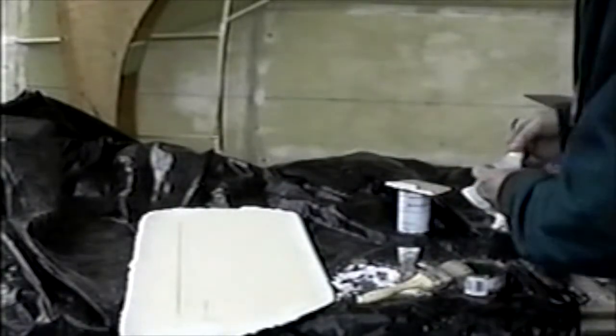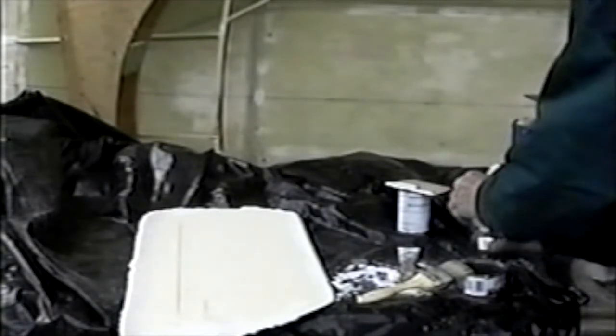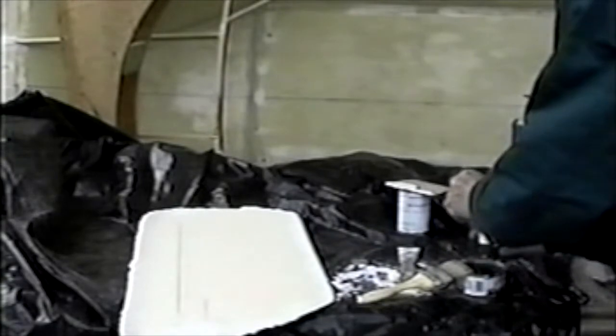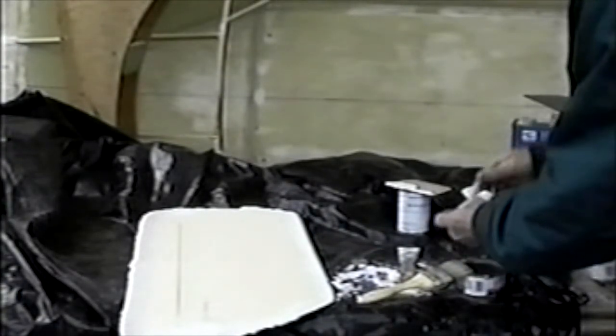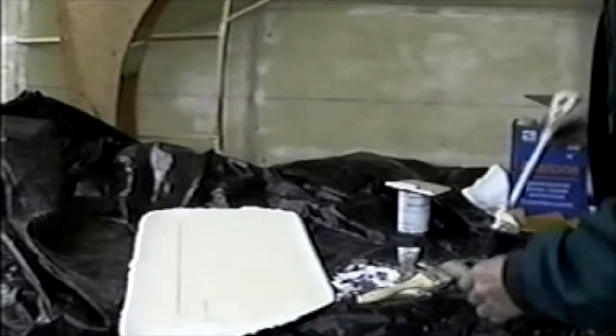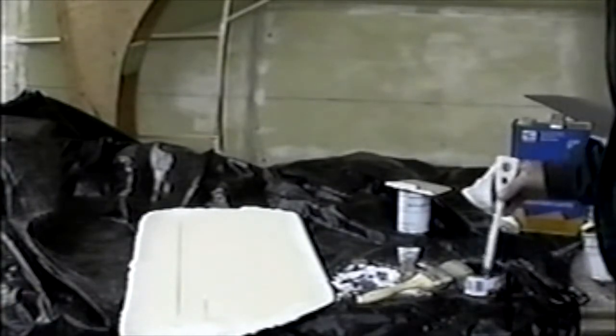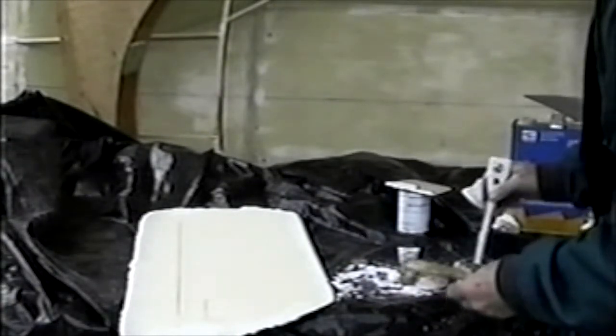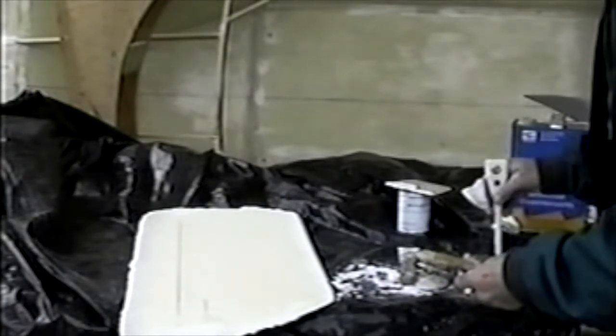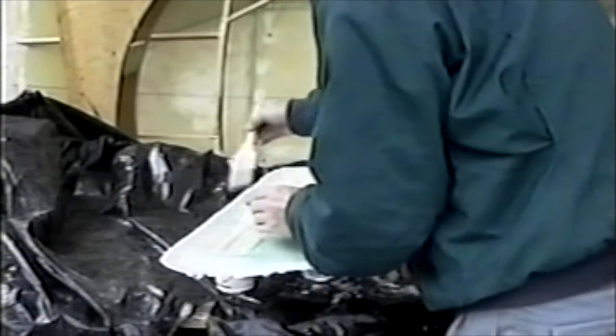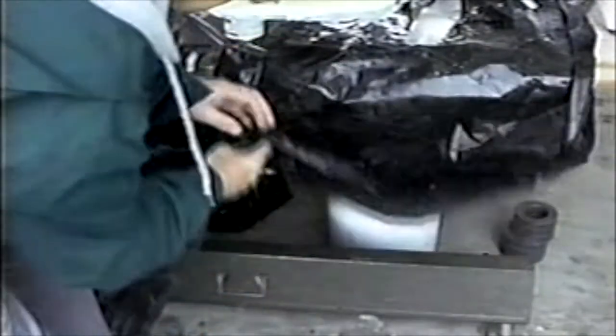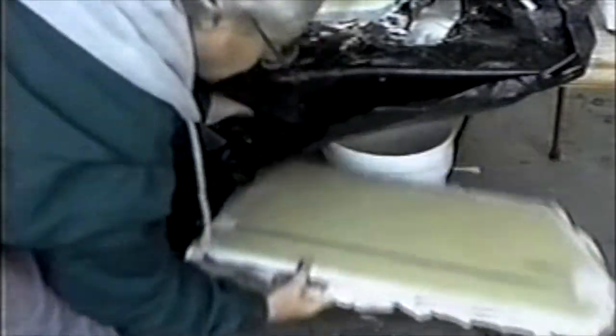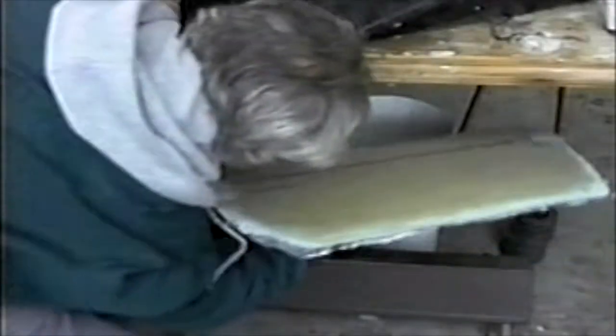Since it's 42 degrees Fahrenheit out here, we're going to catalyze the resin at 2%. We'll also use our heater device that's underneath the table to cure this layup out. It's best to paint the micro balloons with resin before laying the cloth on it, because this tends to smooth the micro balloons out. You'll note that we've raised the panels underneath the heater. This helps considerably in curing out the panels.